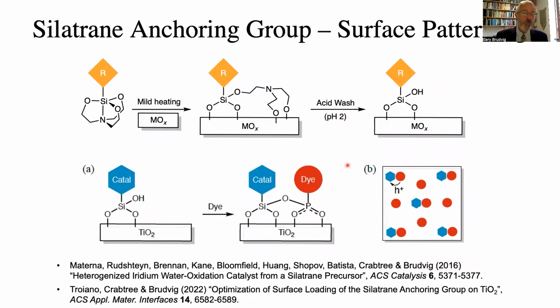More recently, we've been working on a mode of attachment using a molecule called a silatrane. So this is an example of a silatrane. It's a siloxane molecule, but it's protected by this triethanolamine molecule. So it's not reactive. It allows us to incorporate this anchoring group to a molecular complex and carry out synthetic steps, either for dye synthesis or catalyst synthesis. And then by using mild heat, we can deprotect and attach it to the surface using silicon-oxygen bonds to the metal oxide. Very robust attachment.